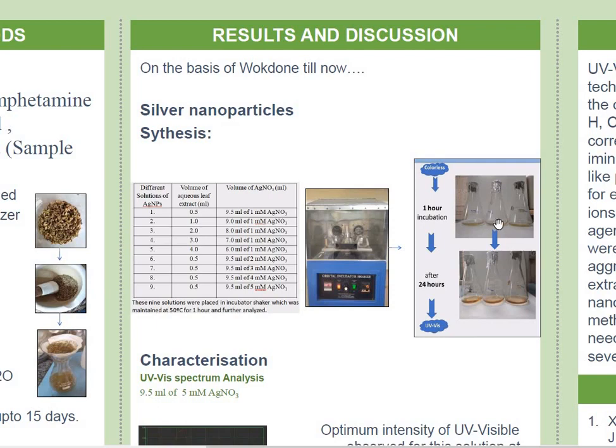So this was the color that was observed, from colorless after 1 hour of incubation, and after 24 hours of keeping at room temperature, finally a dark yellowish color was observed that indicated the formation of silver nanoparticles.